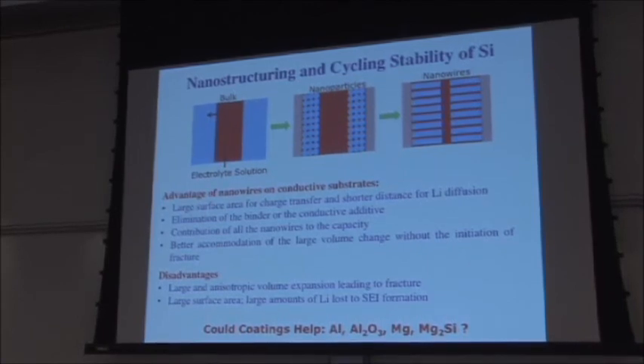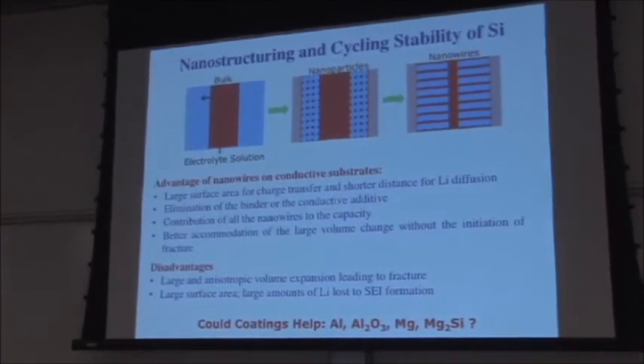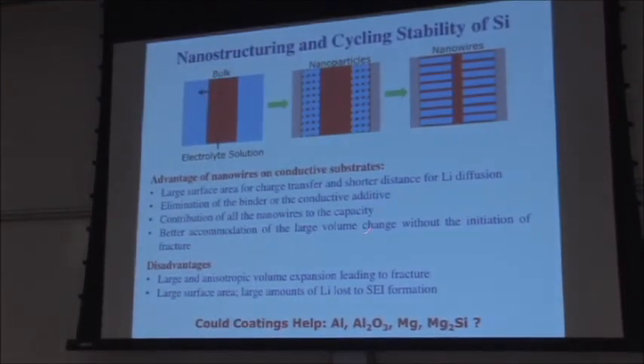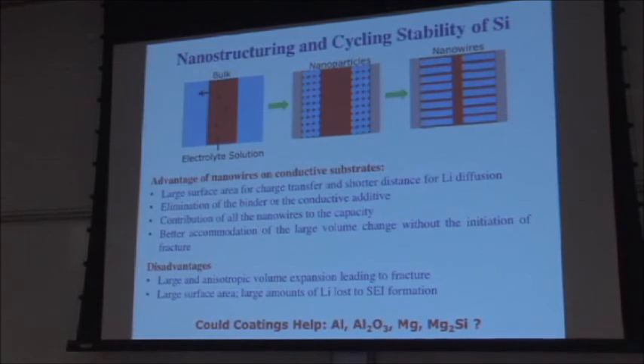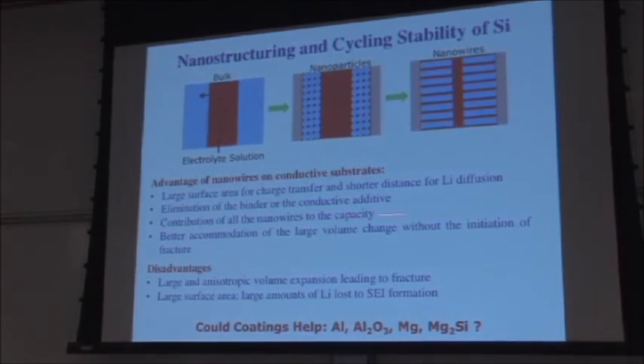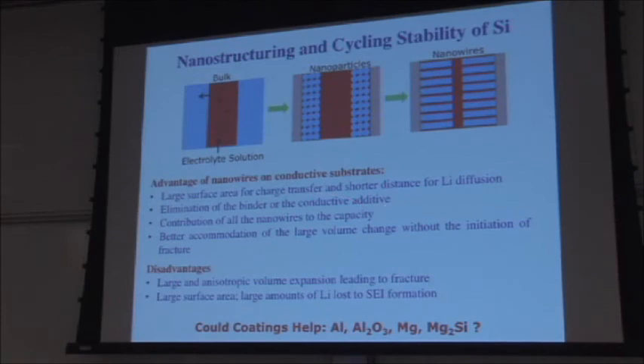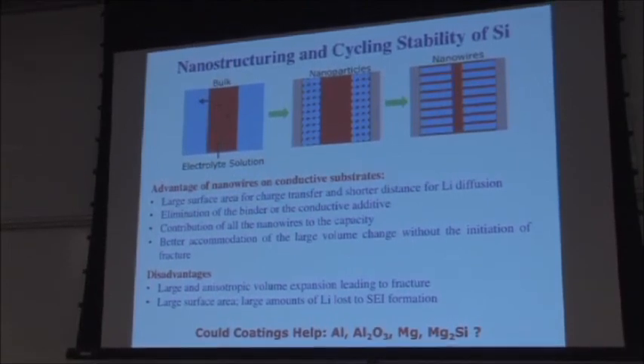So the advantage is you have large surface area for charge transfer and shorter distance for lithium diffusion. You eliminate binder if you're just growing these things on your electrode. That's kind of an artificial one because at the end you will have to achieve a high mass loading, so you'll have to have some binder. In theory, you have contribution of all the nanowires to the capacity. Again, you assume a good electrical continuity. And in theory, better accommodation of large volume changes without initiation of fracture. And there has been a good amount of modeling that shows that below about 200 nanometer diameter, these things should withstand expansion and contraction better than conventional microparticles.